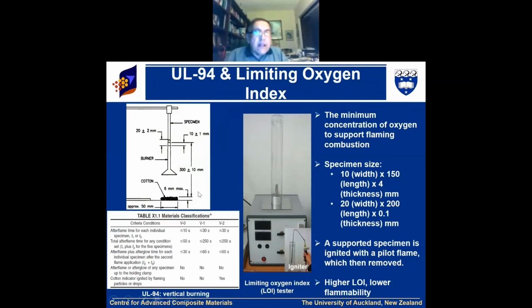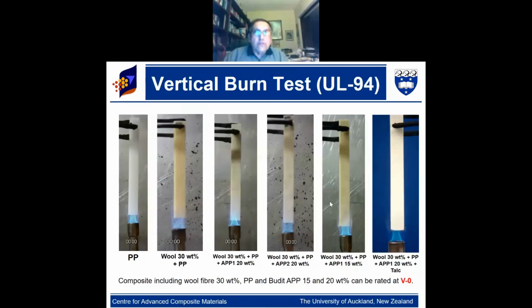This is UL 94, where it says exactly how you should hold the material, how far, and what you should do. There is a cotton wool. You will have to see whether there is dripping or not. And depending on dripping or not, and when the fire starts and when the fire gets extinguished, we get a rating V0, V1, or V2, or no rating at all. So this is the insurance UL 94 test. And limiting oxygen is a much more scientific test. And this is the type of test we do, vertical burn.